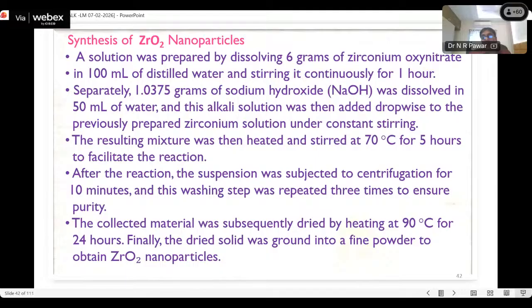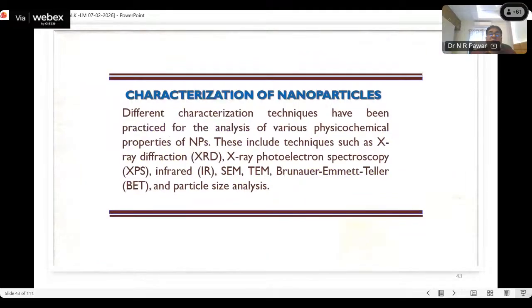After the reaction, the suspension was subjected to centrifugation for 10 minutes, and this washing step was repeated 3 times to ensure purity. The collected material was subsequently dried by heating at 90 degrees Celsius for 24 hours. Finally, the dried solid was ground into a fine powder to obtain the ZrO2 nanoparticle. Now, these 3 particles we use for the synthesis of the hybrid fluid by using various types of base fluid, ethanol, methanol, glycerol, and like that.